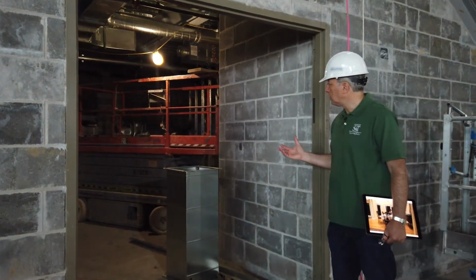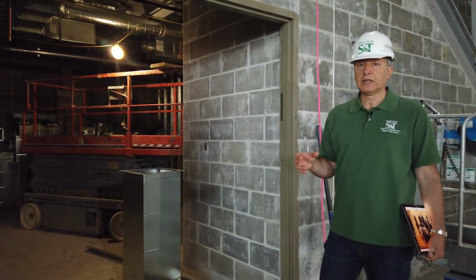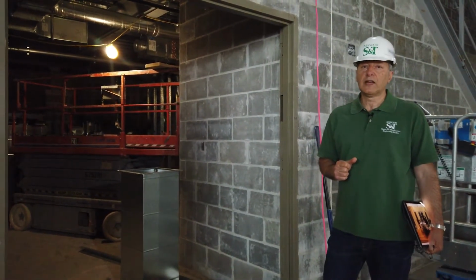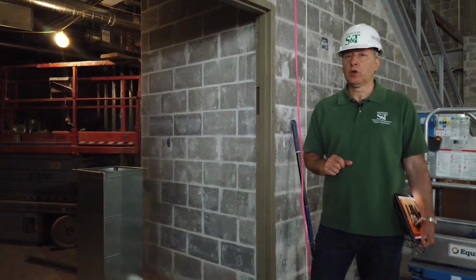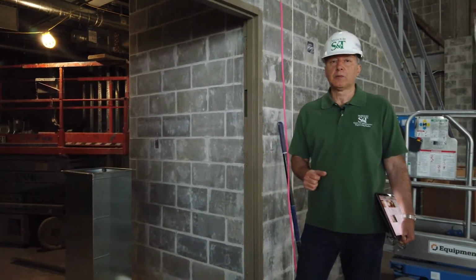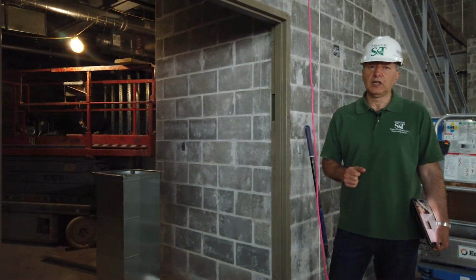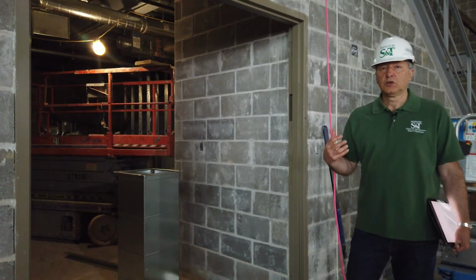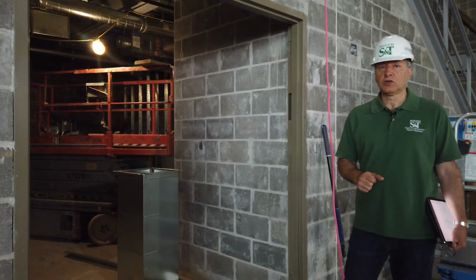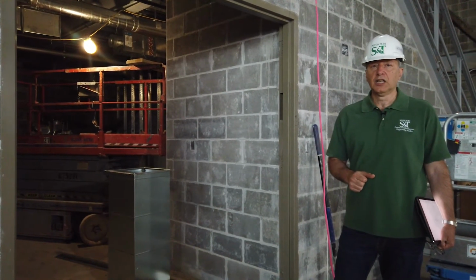This room over here will be holding a lot of very high strength creep cells going at least 10,000, 12,000 PSI active stress. And then it will also have some specimens subjected to 40%, 50% humidity, about 20 degrees Celsius plus or minus, to evaluate the drying shrinkage, autogenous shrinkage, and restrained shrinkage that cause a lot of cracking in concrete structures.